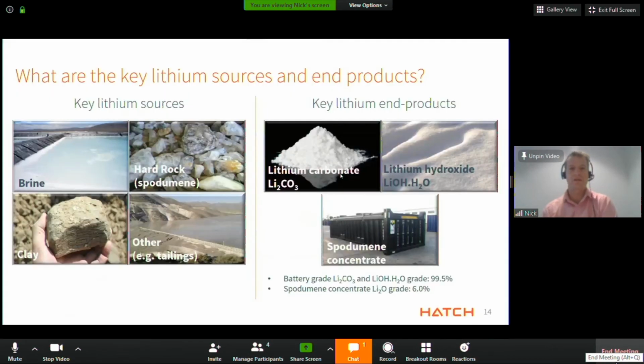So what I want to do is just look within the lithium industry and give people a bit of background around the industry. So fundamentally, there are two main sources. You've got the brine and the hard rock, which is predominantly spodumene. So these account for over 90% of your lithium. Your brines are evaporated lakes, typically in South America, Atacama, for example. And your hard rock is typically spodumene that's found in Western Australia, Canada, and to a lesser extent in China and Brazil. And the two key products, lithium carbonate and lithium hydroxide, are both a fine white powder.